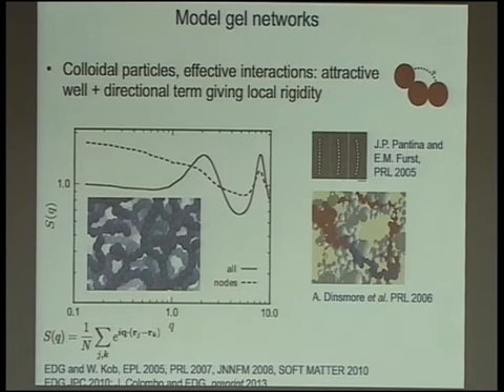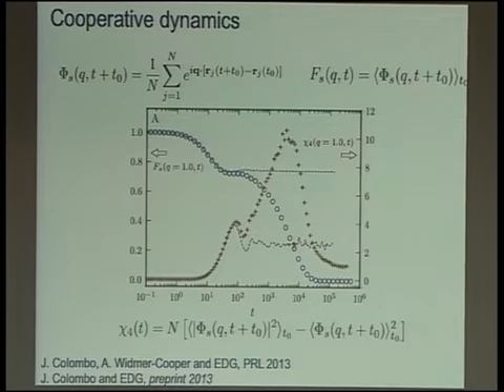As I said before, we have this type of network that is basically chains connected by nodes. And so you can see from this curve, that is the structure factor only of the nodes, that the nodes of the network are not spatially homogeneously distributed, but you can see features of correlation already also in the nodes of the network.